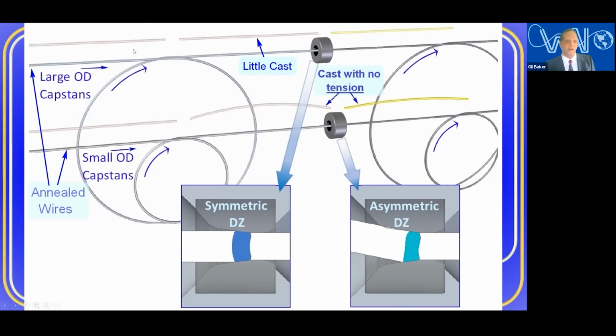So we come through here. This wire starts out straight. This wire, we can assume, also starts out straight. After just the coiling and uncoiling, we have a wire with very little cast for the low wire to capstan diameter ratio. However, when you have the higher wire to capstan diameter ratio, after it comes off coiling, you're going to have a cast in your wire. And this is showing the cast with no tension, meaning the back tension might show the wire straight into the die, but in fact, if you took off the tension, this wire would have a cast to it, or a bowing to it, or a camber.